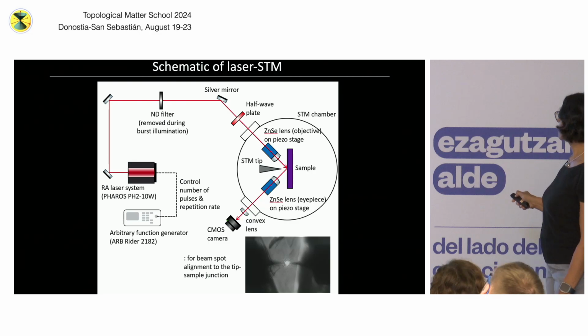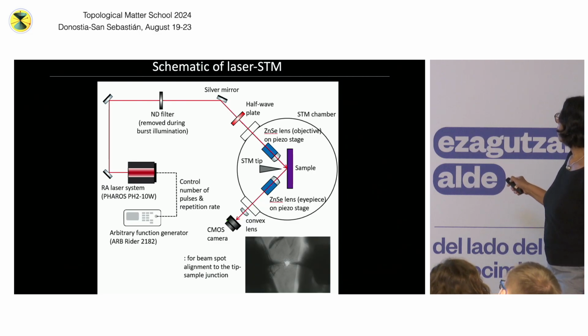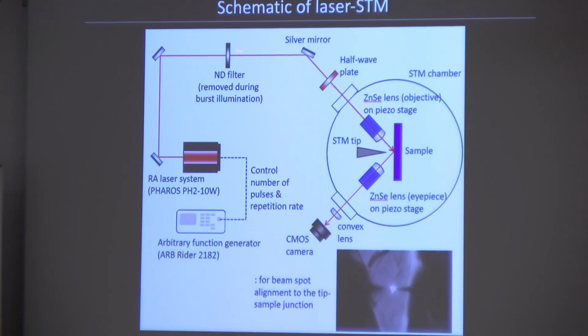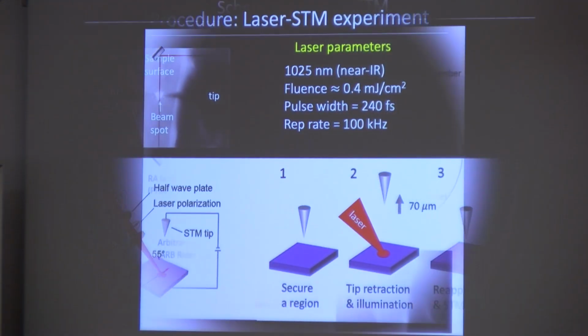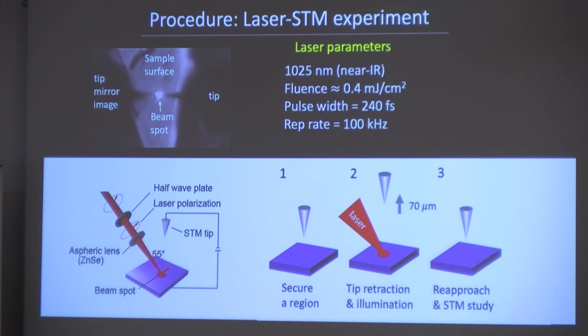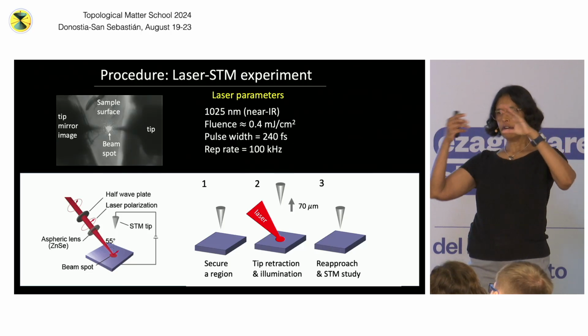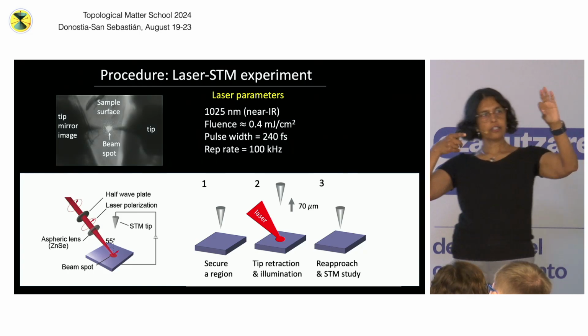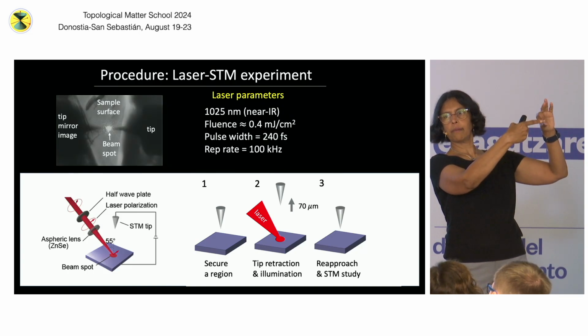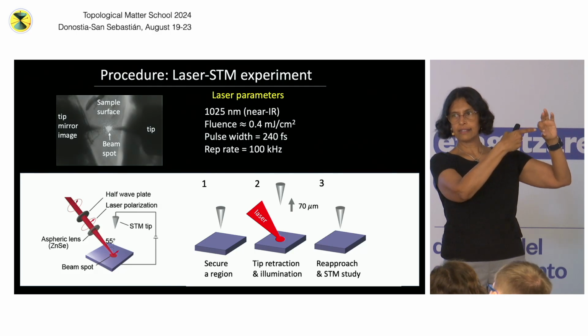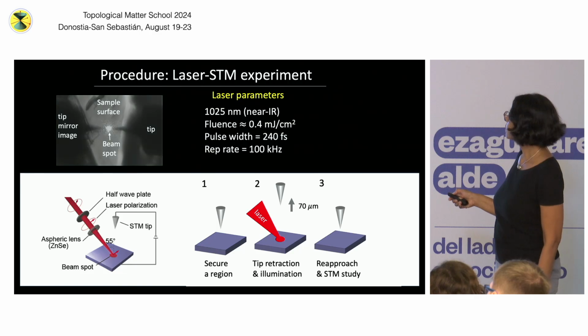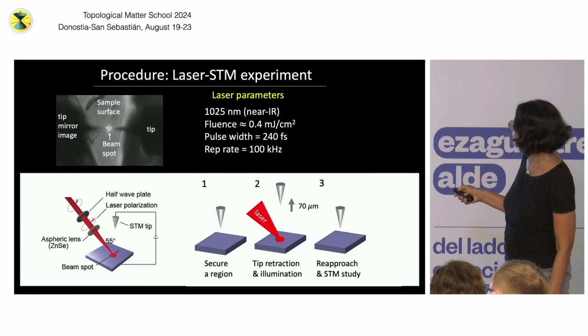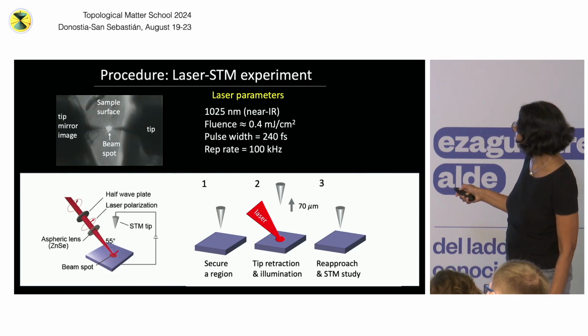Okay, so here's just a schematic. We have the laser, and then we have these two lenses inside the UHV system, and then light comes in, gets focused by these lenses, and here's your sample, here's your tip, and we make measurements using the STM tip. Oh yeah, let me show you. It's here too. Here's something interesting. Remember, the spot size is 10 microns, and your sample is large. So one important thing is here's your spot and here's your tip. You don't want to miss the spot with your tip. You want to be measuring right on where you're shining the laser. And to do that, the other lens is really useful because we can see what you're seeing here: the tip, the STM tip, the sharp thing, and its reflection on the sample.